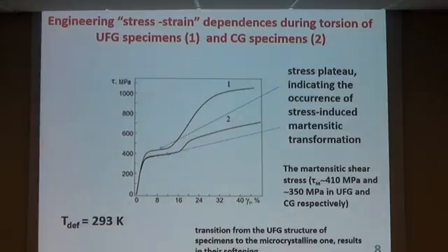In this slide is shown the engineering stress-strain dependence during torsion of ultrafine grain specimens and coarse grain specimens. It is a stress plateau indicating the occurrence of stress-induced martensitic transformation. Martensitic shear stress is about 400 in ultrafine grained and coarse grained specimens. Transition from ultrafine grained structure of specimens to coarse grain results in this softening.